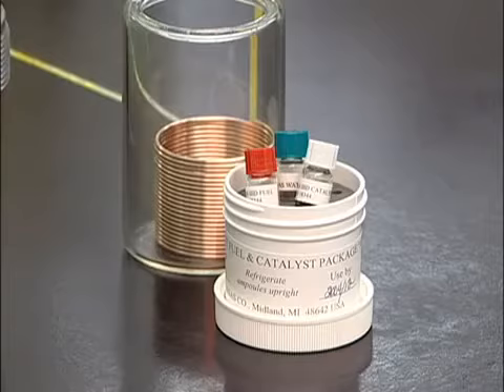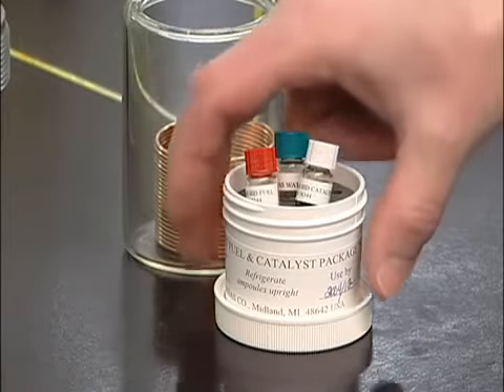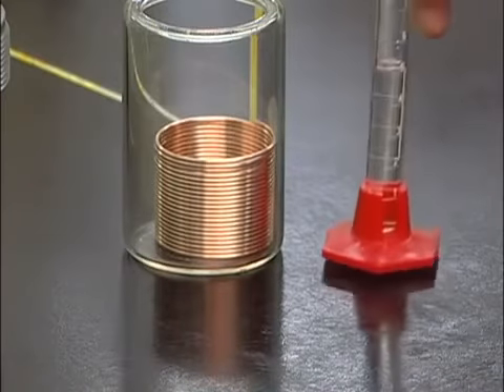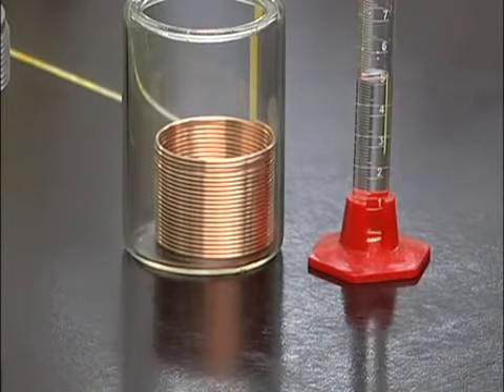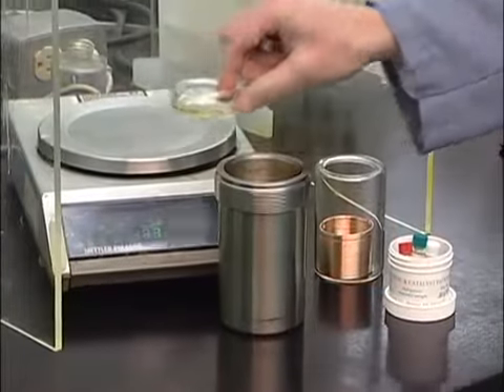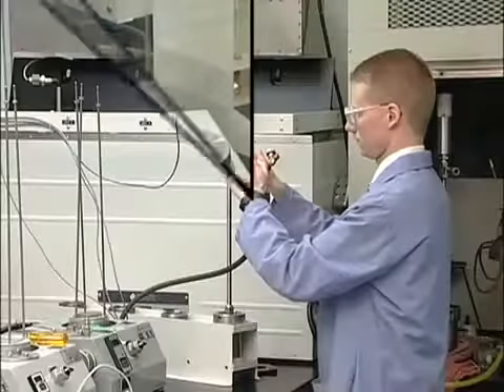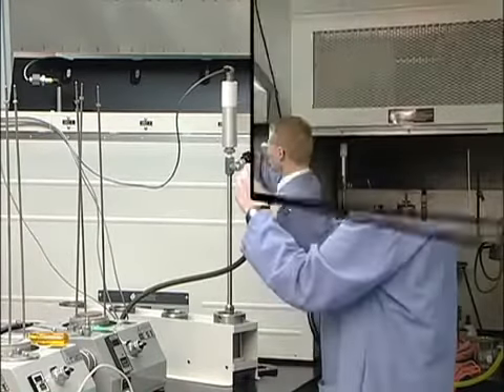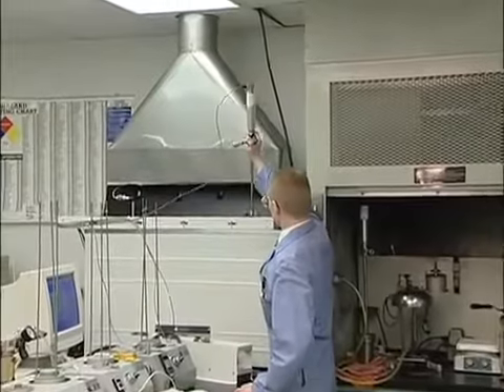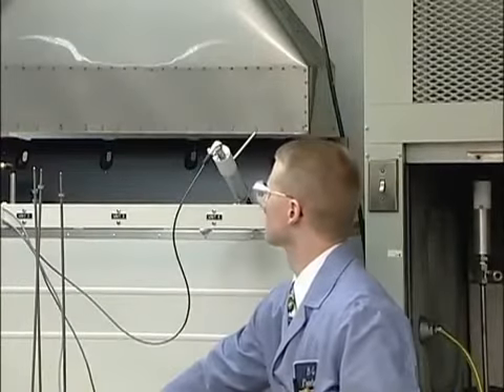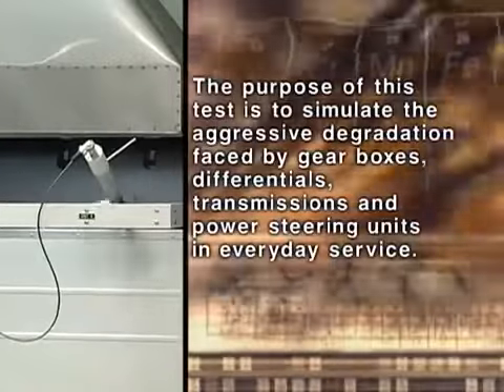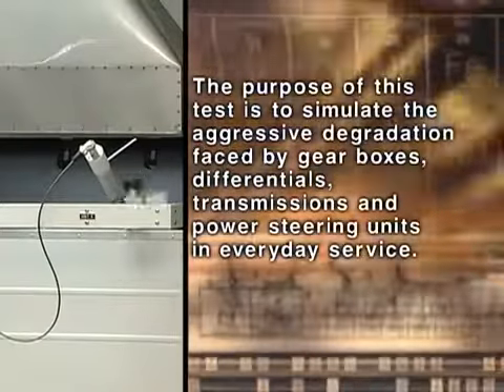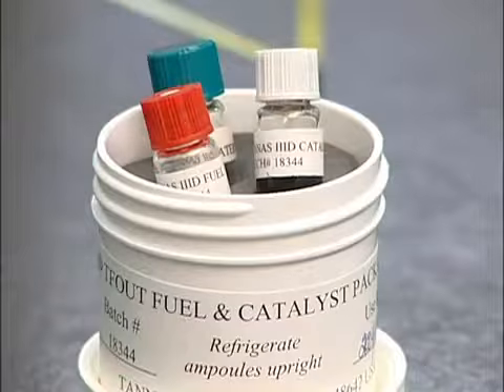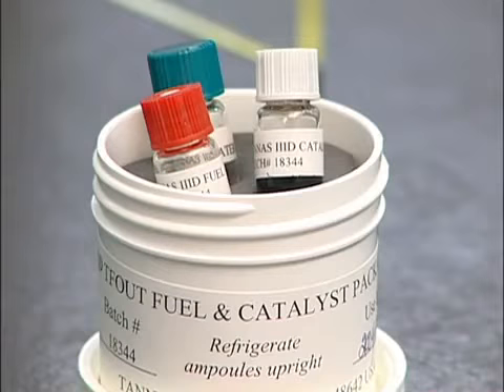For the RBOT ASTM D-2272 test, the catalyst will be copper and water. A prepared sample consisting of 50 grams of the oil to be tested, 5 milliliters of water, and the copper catalyst is placed in the bomb, which is then pressurized to 90 psi with oxygen, immersed in a hot oil bath set at 150 degrees Celsius, and rotated at 100 RPM. The purpose of this test is to simulate the aggressive degradation faced by gearboxes, differentials, transmissions, and power steering units in everyday service.